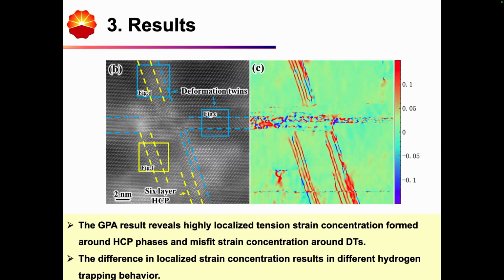For the deformation twins, we can see a series of misfit points, and hydrogen tends to be trapped at the misfit points. So the trapping behavior of the deformation twin and the trapping behavior of the HCP phase are slightly different.